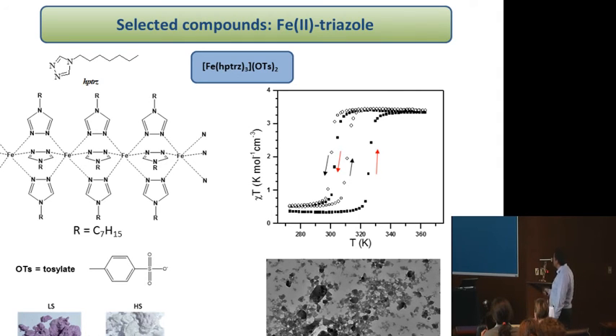Here we can see the color change of the samples. This is a picture of the normal powder, because we want to synthesize nanoparticles, but you have to know what we have inside the bulk samples. If you look at the bulk sample, you have different sizes, from a few tens of nanometers to micrometric, but you have polydispersity. So this is not convenient if you want to go toward applications. This is why we try to synthesize homogeneous nanoparticles.